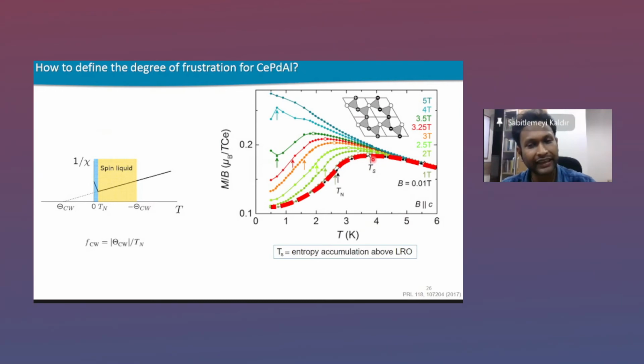Now what they have seen is that Ts is actually the point at which there is a high entropy accumulation above the long range ordering. And we also know from our basic understanding that in a frustrated system, you are always going to expect a high entropy accumulation above the ordering temperature because of the presence of frustration. So what they said is that instead of this Curie-Weiss theta in a metallic system, you can consider that this Ts might to some extent dictate where the system would have ordered if there would not have been any frustration.